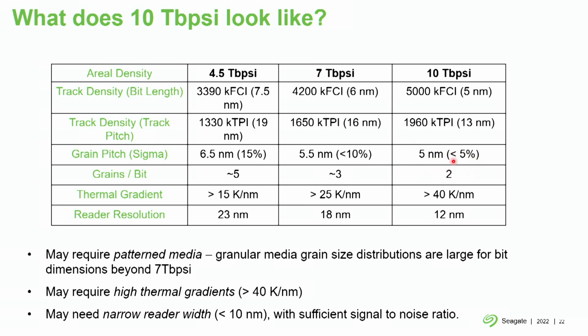But also the grain size distribution has to be pretty narrow, because if I have a very large grain size distribution, then some of the grains will be really large and may not be written properly. Some of them will be small and will be overwritten. So not good unless we have a very good distribution. It'll be 2 grains per bit, so another reason why we need good grain size distribution. The thermal gradients are going to be much higher. This is more than double what we have today, because we would need to scale the geometry of the near field transducer, which will naturally lead to higher thermal gradients. And then the reader resolution will have to be much, much smaller than it is today. So we would need readers that are much smaller than 10 nanometers to be able to achieve these resolutions. So if we were to keep the architecture the same, the requirements for 10 terabit per square inch don't look very achievable.